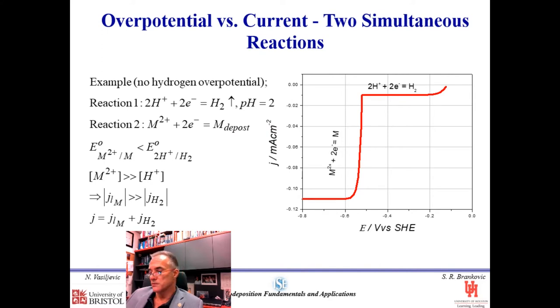One thing that is important to appreciate is that generally when we do electrodeposition of metals, not all the metals deposit only as a pure or single reaction. Generally, we also have situations for the metals that are less noble than hydrogen, that hydrogen or hydronium ion reduction, or hydrogen evolution reaction, goes in parallel. And this is very common for iron, cobalt, nickel, zinc, and other metals, lead deposition, cadmium, etc.